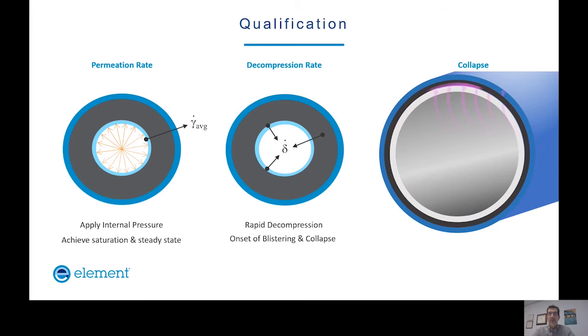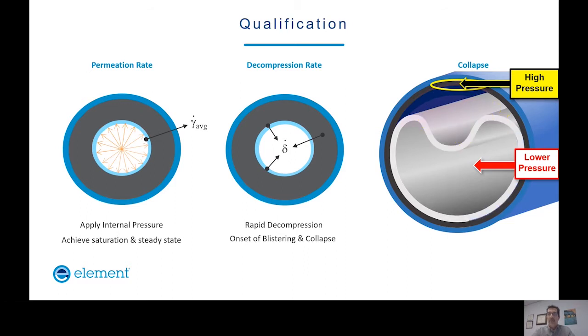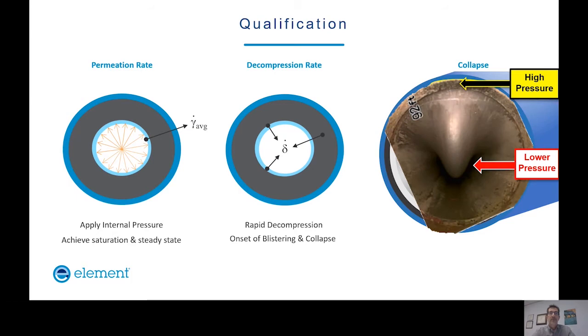As an example, again, these molecules of pressure that permeate through the wall can collect in various positions throughout the wall thickness. During normal conditions, we have a high pressure zone within the wall. We also have a high pressure zone within the ID of the pipe. If we come into a condition where we lower that pressure, we have the potential for that liner and any one of those layers to collapse due to the high pressure that's accumulated by those molecules transferring through the wall. If you run your camera or a pig or something out in the field, what this looks like is from the bore, you see what seems to be a protrusion, almost like tonsils hanging down. That's what would be called a collapse of the liner if you see that in the field.